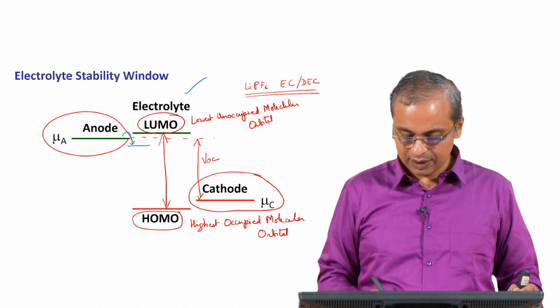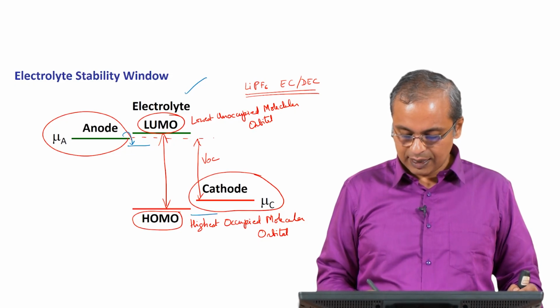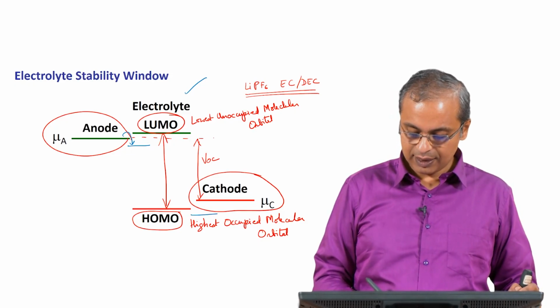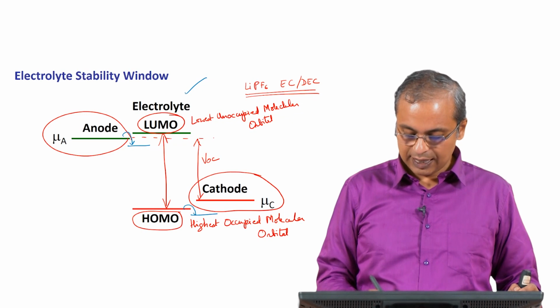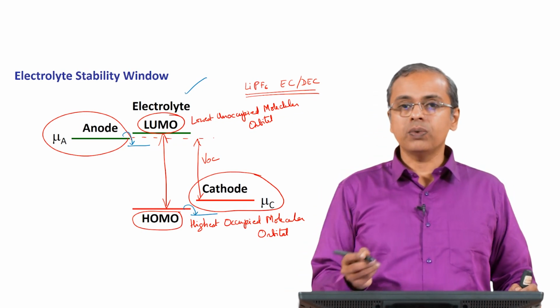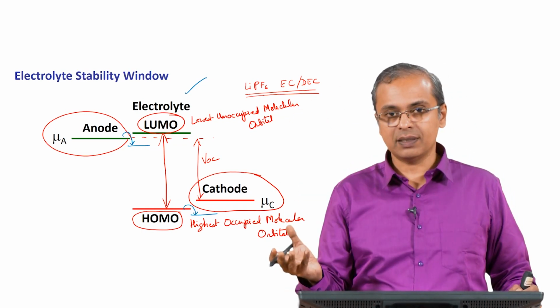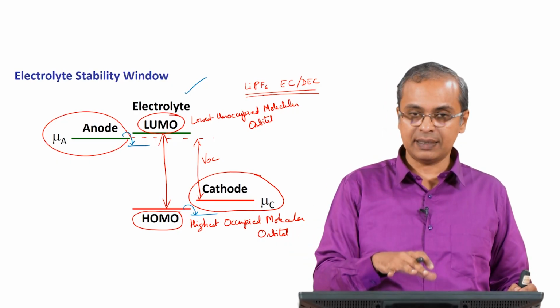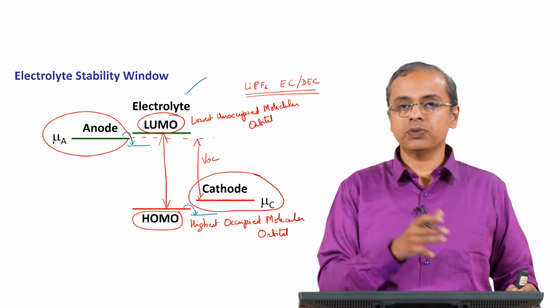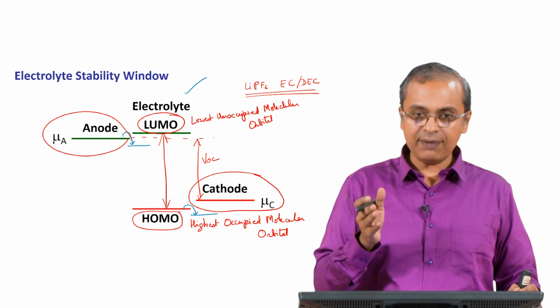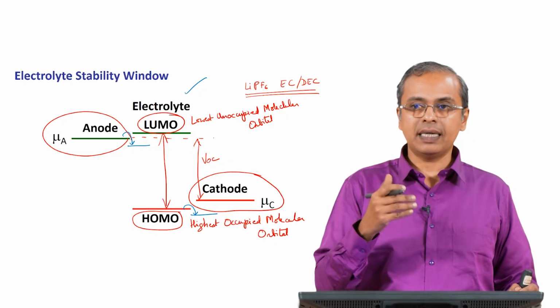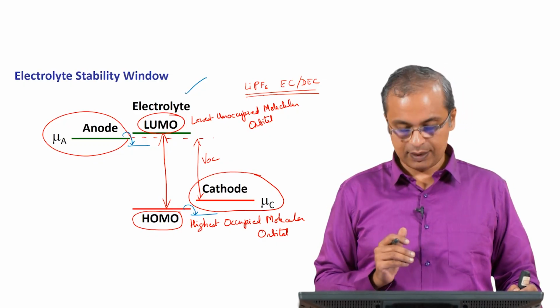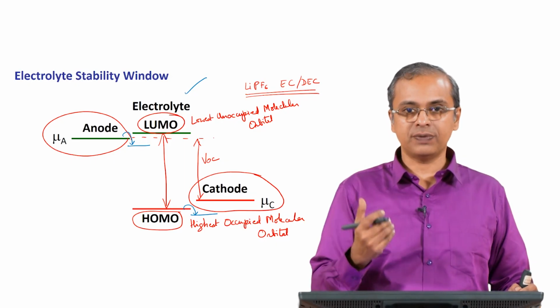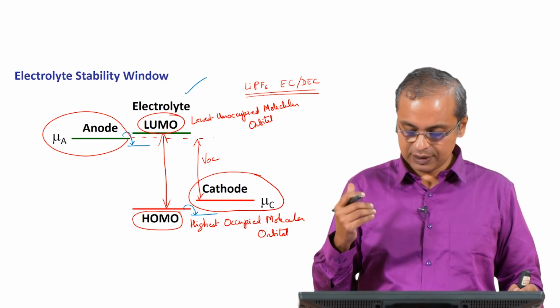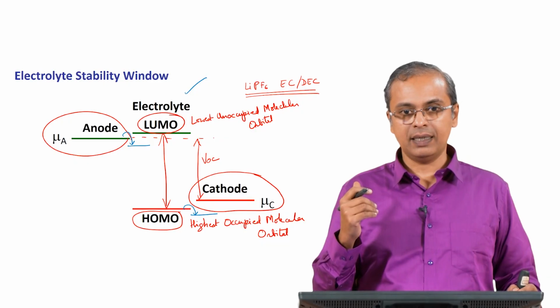And similarly, if the cathode were lower here, as the cathode gets reduced, it will take the electron from the electrolyte. So, now instead of having electrons being released to the external circuit, they will get consumed by the electrolyte itself, based on the position of the electrode, right. So, you will have the electrode reacting with the electrolyte, and that will basically spoil the cell, you will not get energy out of the cell, and therefore, this is not something that is desired.